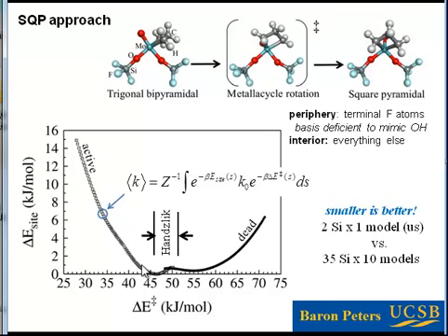And when you rate weight the distribution, that is, when you ask the question, if I have sites that have populations according to something like a Boltzmann factor, but then I multiply that Boltzmann factor by the rate at which the catalysis happens on that site, that shifts the whole distribution to the left. And you can make an argument that the dominant part of the distribution of sites, at least for catalysis, is over here on the left, probably entirely missing this part of the distribution of active sites that was studied by Handzlik.